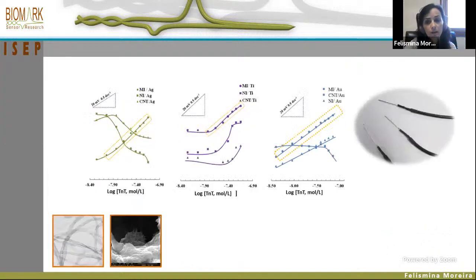So we also used a very cheap and easy electrode system. We entrapped the nanomaterial in one polymeric membrane based on PVC and one solvent mediator to allow the flow of the ions, and we immobilized the membrane, drop casting it on the electrodes, and we studied the operational features of the sensor with the potentiometry technique.